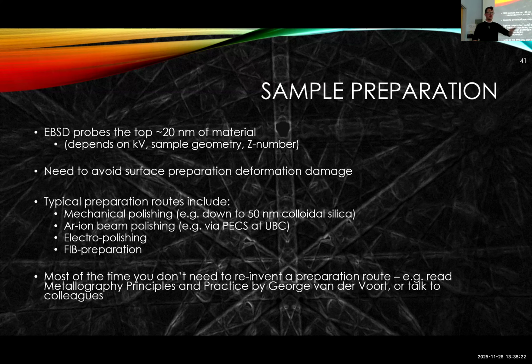So we do metallographic polishing. We look at cleavage surfaces. We look at as-grown crystals. We use ion beam systems. We use electropolishing. We use the FIB. It depends on the problem that you're working on. But sample prep is half of the knack.